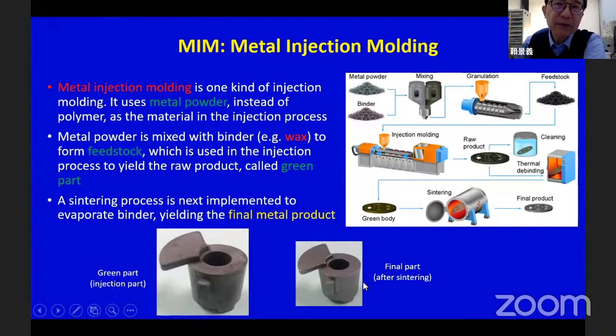For a lot of products, they use this kind of process to produce the part because it uses injection molding, so the production efficiency is quite good. For example, if you want to produce 1,000 or 2,000 parts, it takes maybe only 1 or 2 days to get the final result. But if we use CNC machining, each part may take maybe 1 or 2 hours. So for CNC machining, the efficiency is not so high. This is the main reason for using metal injection molding.